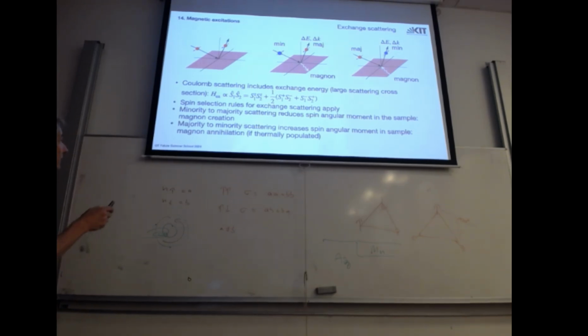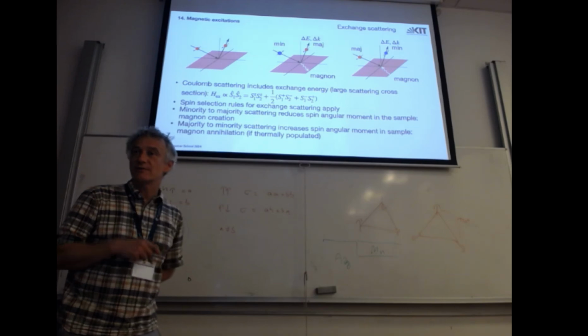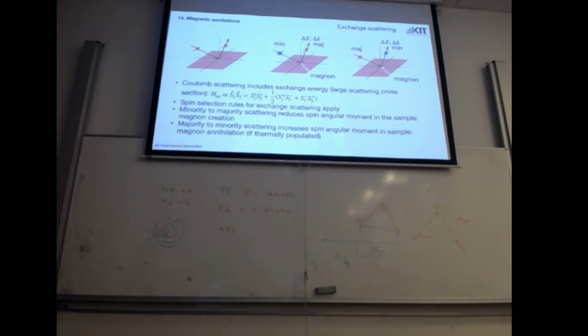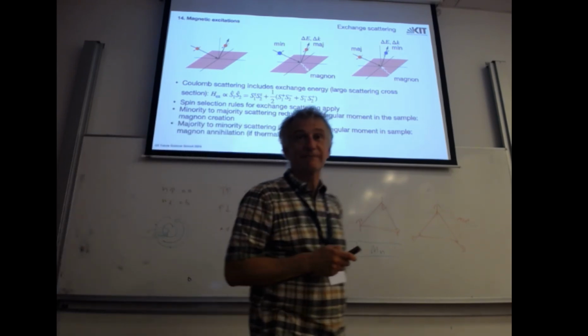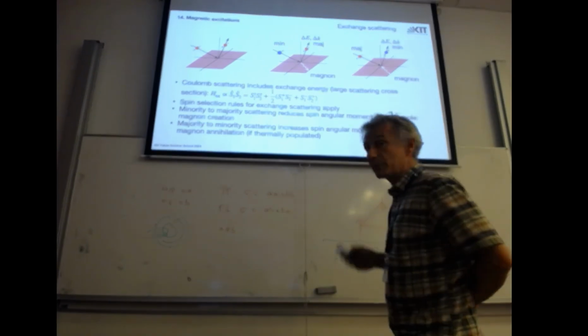So there's one channel which is non-spin flip. I get scattering of my electrons from the surface, with momentum transfer and energy transfer, by phonons or whatever, but the spin is not changed. So this has nothing to do with magnetism. We have no phonons actually, only scattering and reflection. So it's like non-spin flip in neutron scattering. But there are spin flip processes.